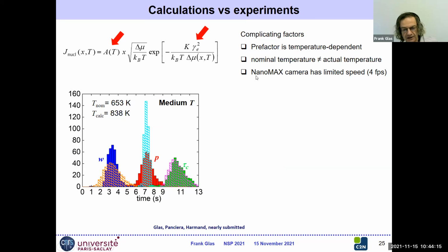And the other complicating factor is that the NanoMAX camera, of course, has a limited speed, and the data that I present here were acquired with 4 frames per second. So the game would be to try to reproduce all our experimental histograms with a single set of parameters for the nucleation rate. So I show you at the moment the best that I obtained. The full histograms here are the experiments, and the histograms with stripes here are the calculations.